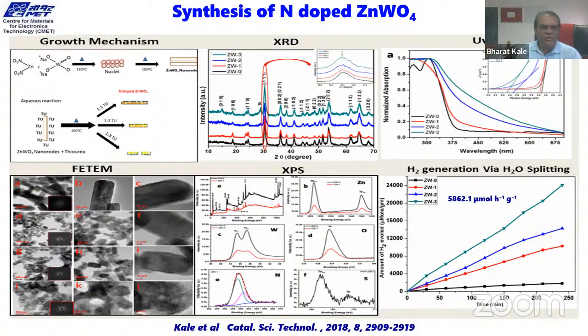ZnWO4 is UV active. Then what we thought is whether we can make a nanostructure of ZnWO4 and whether we can take this ZnWO4 into the visible region by modifying with nitrogen doping. The beauty of nitrogen doping is that a small amount of nitrogen just replaces the oxygen in this ZnWO4, and the band gap changes from the UV region to the visible region. You see here is the UV visible spectra. Initially ZnWO4 absorbed at 375 nanometer. When we dope with nitrogen, with the nitrogen content, you can see that there is a change in the absorption to the visible region. So it's very, very important.